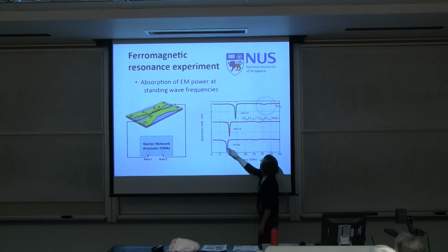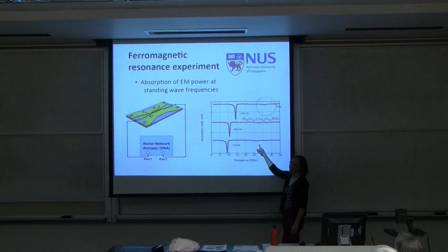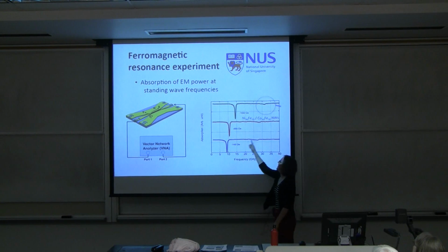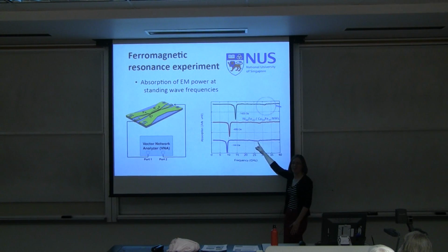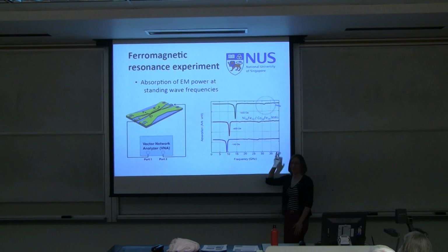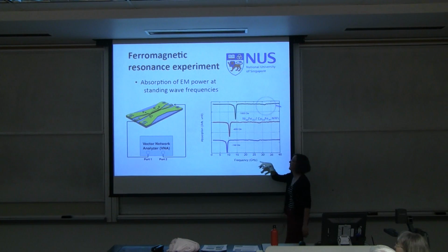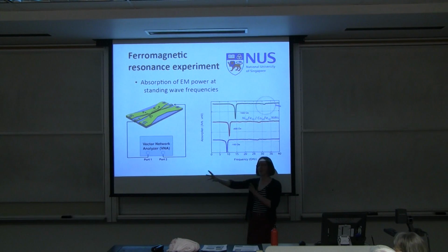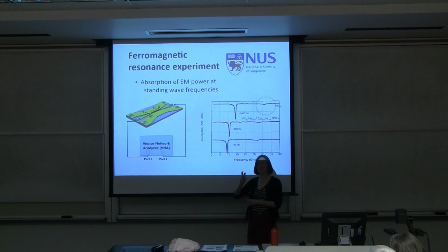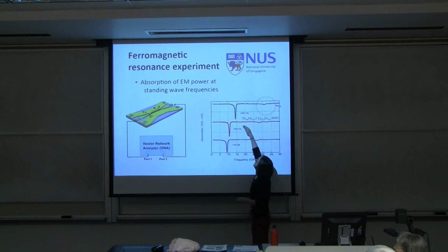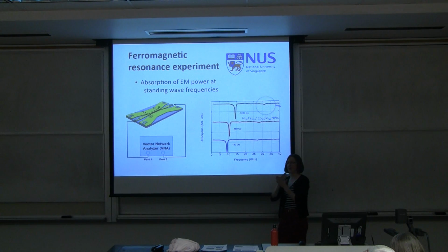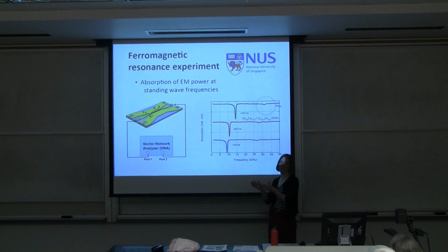Okay? Now there's also a little blip here, and with more resolution we could see that. This is a second standing spin wave mode, okay? And there's less absorption for that for reasons I'll talk about later on. But the point is you send microwaves through, where you see a strong absorption, that's where your standing spin wave has to be. And these three curves are for different values of the static applied field. So as you change the magnetic field, you're going to change the properties in the magnetic system, and your standing wave is going to have a different frequency associated with it.